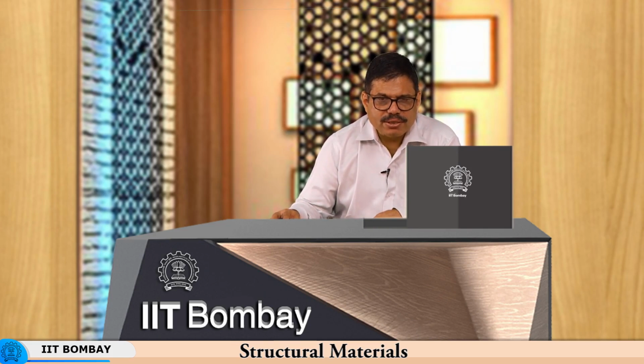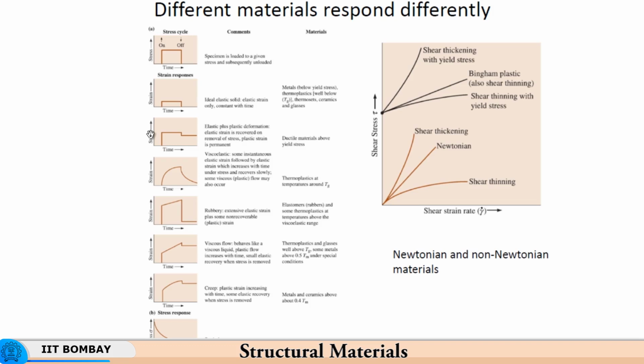And then thermosetting plastics, ceramics and glasses would obey this ideal elastic solid stress strain relationship. On the other hand, you have here another response of the material, because now you are applying a certain amount of stress, but the yield strength of the material is much lower than the stress which has been applied over here. As a result, it changes into a plastic state, and on the removal of the load here, you see that there is some permanent deformation that is retained. So, the deformation does not fall to 0 as in case of elastic solid.